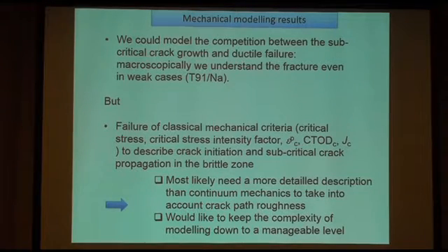So it's most likely that we need a better description of the material to be able, in particular, to take into account the crack path roughness, meaning that the path is intergranular and probably has discontinuous propagation, and we need to be able to model this process to probably go back to some mechanical criteria for its correct description. Additionally, we would like to keep the complexity of modeling down to a manageable level.